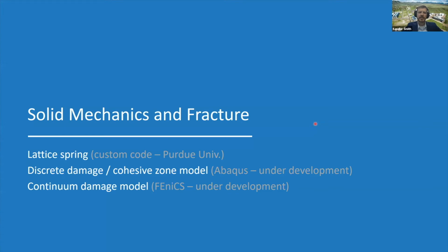Okay, next, this gets into a little bit of our efforts on incorporating solid mechanics and fracture into macro-homogeneous models, standalone models, as well as what we'd really like to do is to incorporate this into this 3D microstructure model. This is still kind of a difficult task. We've got some early steps towards this. Working with Purdue University, they have a custom lattice spring model, which I'll describe. To finely resolve a NMC particle, right now we're working with an Abaqus cohesive zone model, describing damage just at the grain boundaries. And then also we're working on developing this and scaling this up into our 3D electrochemical model, which is in the FEniCS environment. FEniCS is an open source code, finite element based, which scales well on high performance computers.